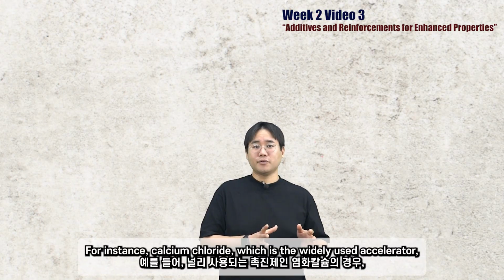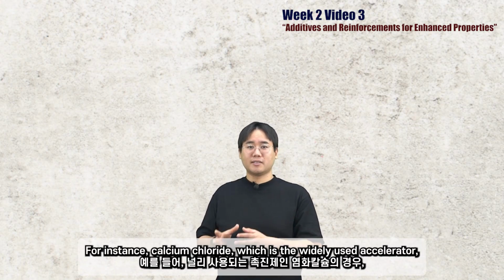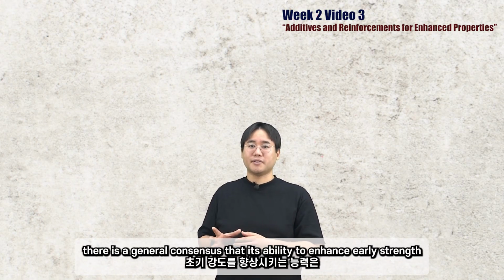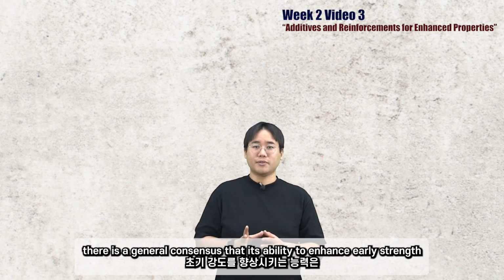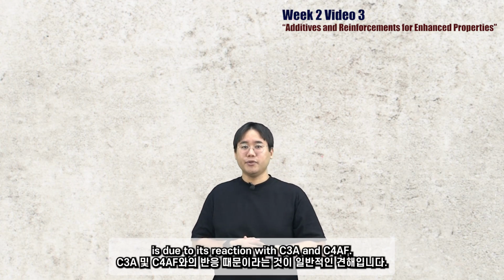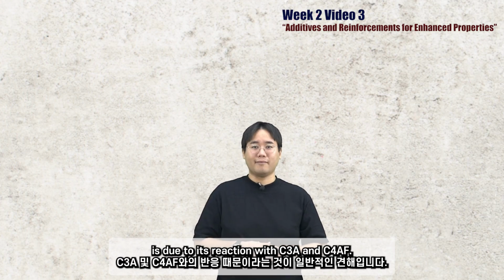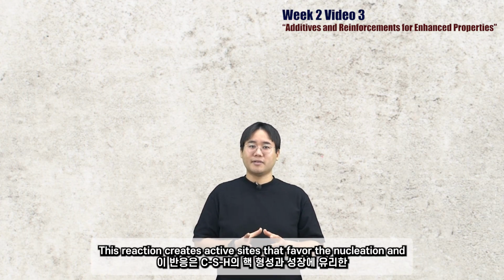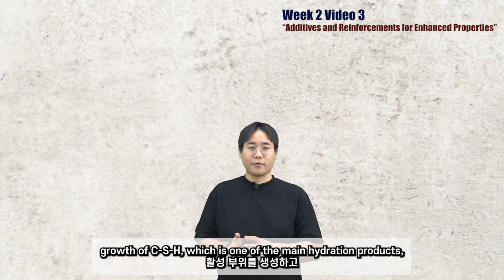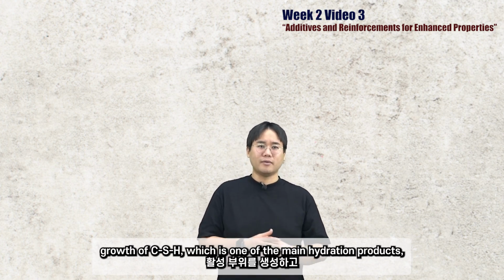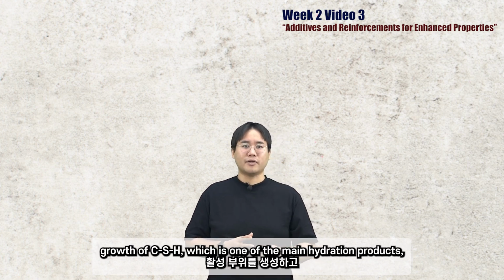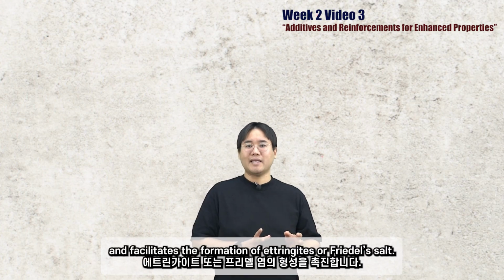For instance, calcium chloride, which is the widely used accelerator, there is a general consensus that its ability to enhance early strength is due to its reaction with the C3A and C4AF. This reaction creates active sites that favor the nucleation and growth of CSH, one of the main hydration products, and facilitates the formation of ettringite or Friedel's salt.